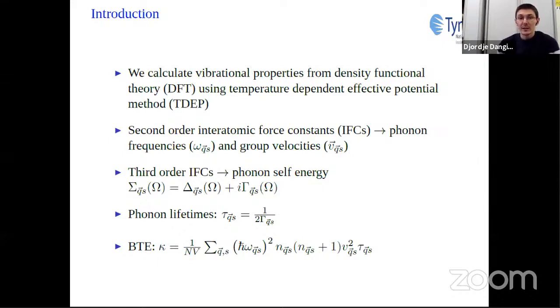For example, the second order interatomic force constants give us harmonic phonon properties, such as phonon frequencies and group velocities. Third and higher order interatomic force constants give us phonon self-energy, which measures the interaction between phonons. This phonon self-energy is a complex function of frequency for each phonon mode. The imaginary part of phonon self-energy gives us the phonon lifetimes, as shown here. Then we use these properties calculated from first principles in the Boltzmann transport equation expression that I showed in the last line here to actually calculate the lattice thermal conductivity. Here, just to note, this N denotes the phonon population at certain temperature, which is calculated as a Bose-Einstein occupation factor.